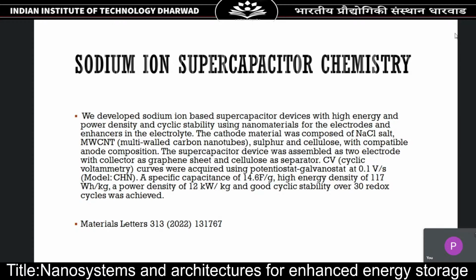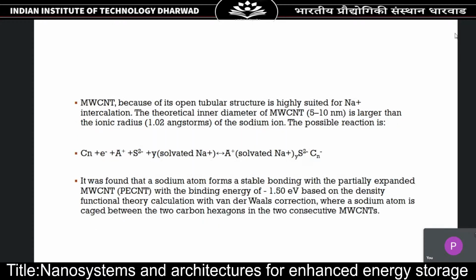So what was the reason for using multi-wall carbon nanotubes? This was published in Materials Letters recently. Multi-wall carbon nanotubes have a very open tubular structure, and are very highly suited for sodium intercalation. The theoretical inner diameter of MWCNT is about 5 to 10 nanometers, and a sodium ion is only about 0.1 nanometers. So you can see that it can very easily intercalate and deintercalate.